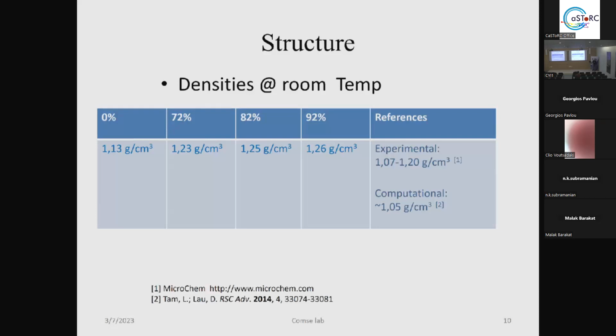The cross-linking process? Because the cross-linking process by itself is a very difficult thing, okay? I proposed that, and finally this is what we did: we followed an already existing algorithm proposed about 2010, if I'm not wrong, by Lee and Strachan. This algorithm is based on geometrical criteria and energy minimization, and follows a molecular dynamics route at very high temperatures in order to be as fast as possible. For small systems like 4,000 atoms, it took some hours, let's say. But for bigger systems that we see now with the PhD student, it takes about half a day or like that. So again, it's very logical, time.